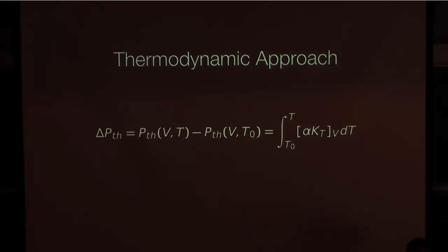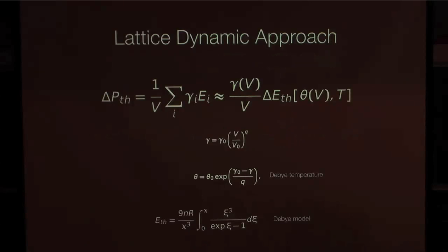So I will assume them a constant, and then use one bar value of alpha and one bar value of KT, which works pretty fine until the early 90s. But once you have better resolution and precision, now you start discovering that that assumption is not actually good enough. So there's a more rigorous approach, the so-called Debye approach, that is implemented in Burnman.